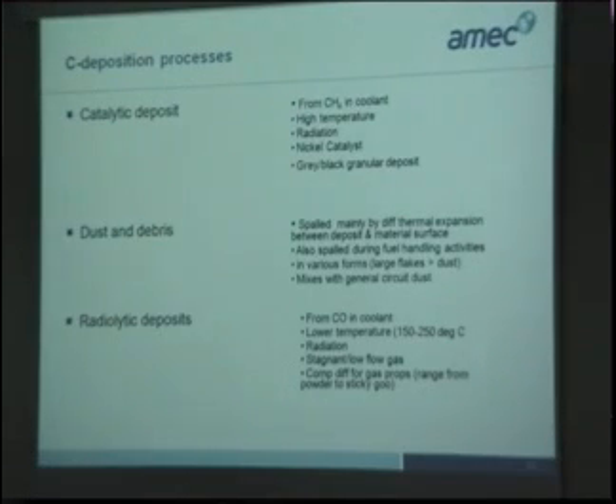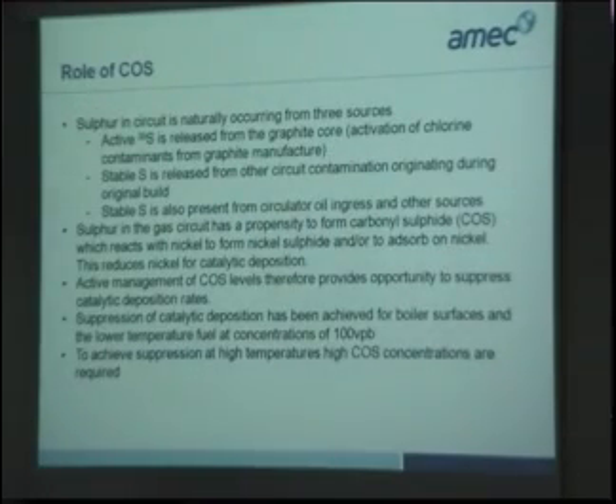There are other types of carbon deposition processes. We've just talked about the catalytic deposits. There's also dust and debris from thermal expansion of deposits in the material surface, and also radiolytic deposits which are found in the fuel route. But the main concern is the in-reactor catalytic deposit. And this is where carbonyl sulfide comes into play. Carbonyl sulfide will act as a poison to any nickel catalyst that's deposited on the surface. We already have sulfur 35 in the circuit naturally, and it was found that reactors which had oil leaks, the gas circulator oil leaks, in other words there was a higher amount of sulfur in the circuit, were found to have less carbon deposition than the other reactors.